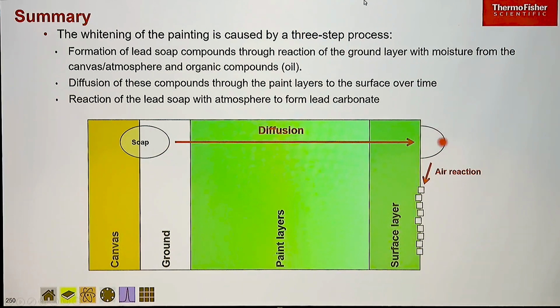So that bubble we saw on the surface of the painting, that was one of these bubbles of palmitates, that lead palmitate that's come up to the surface. It reacts with the air in the gallery then, and so through just interaction with the carbon dioxide in the air, or even oxygen, that forms then into small crystallites of lead carbonate. And so as these bubbles get consumed, they form these little crystallite structures, and we get this effect of these covering over the green paint and going from green to white. And so that was what was changing the surface of the painting and changing the colour from green to white.